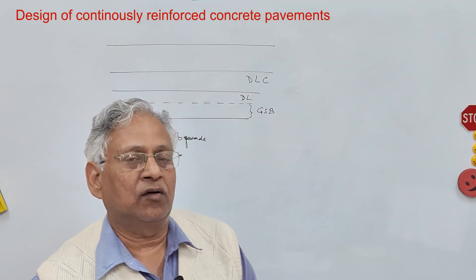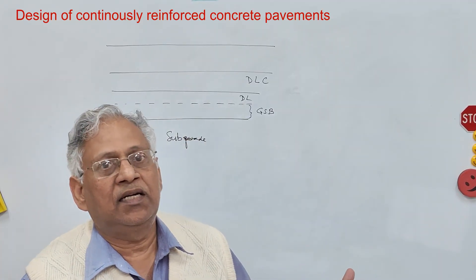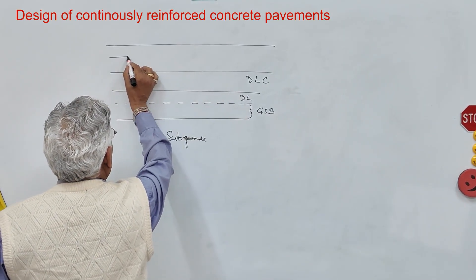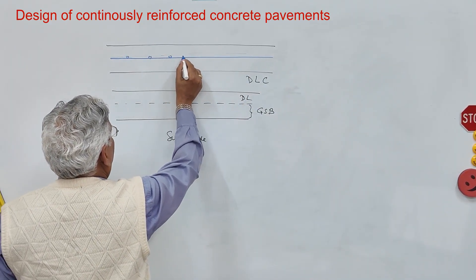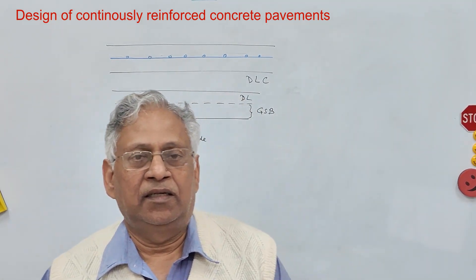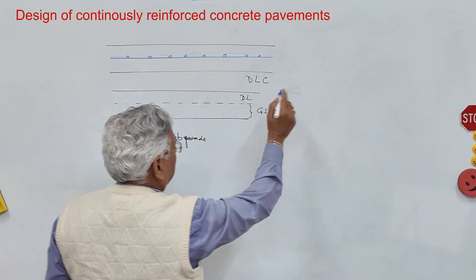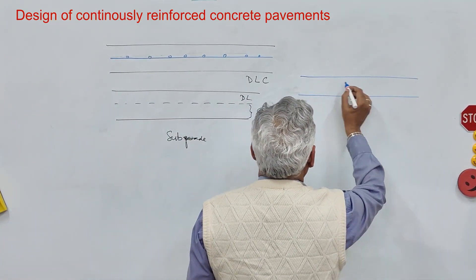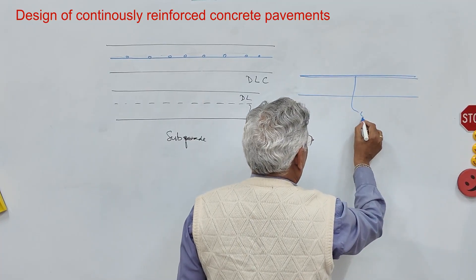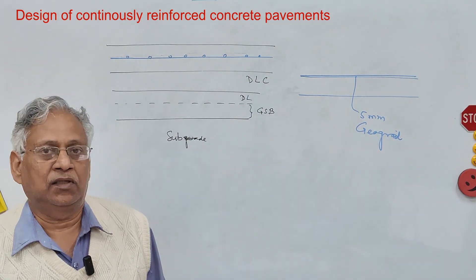The concrete slab thickness generally varies from 250 to 300 mm for traffic conditions generally prevailing in the country, but it is to be designed as per IRC 58 for the full load spectrum. Within this slab, reinforcement is provided in the longitudinal direction as well as in the transverse direction. Design of CRCP basically means designing the pavement as per IRC 58 and then designing the reinforcement. If the base is a bituminous layer, rather than providing PQC directly over DLC, a geogrid layer of 5 mm thickness is provided, above which the pavement quality concrete of desired thickness is placed.